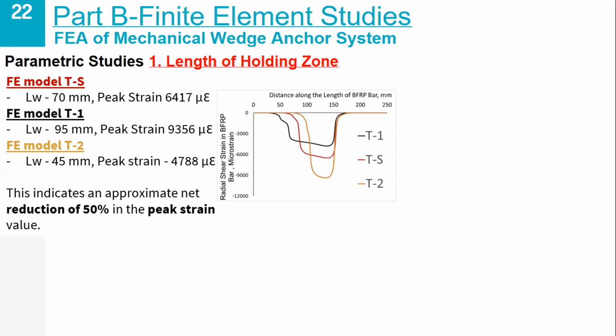So 3 different models with 3 different length of the holding zone of the anchor has been investigated, and the peak strains has been obtained as shown in this slide. And it indicates that there is an approximate reduction of 50% of the peak strain when you change the anchor length from 95 millimeters to 45 millimeters.